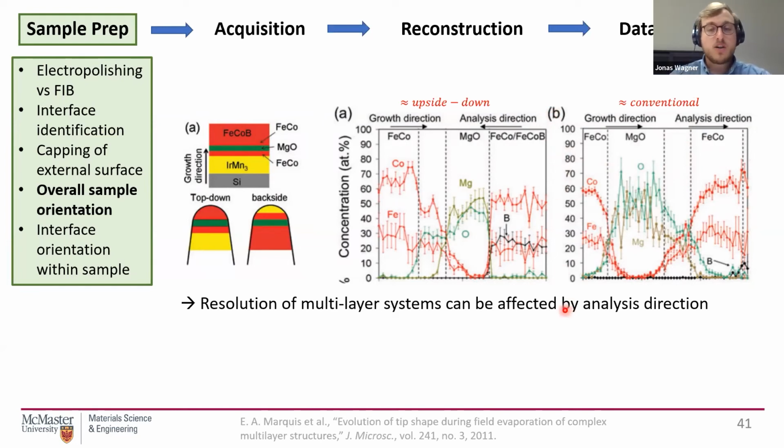Sometimes it doesn't work as well. For example, I also tried it with my sample, but because I had the oxygen contamination, having this oxygen contaminated layer between the post and the sample proved to be detrimental to heat transfer. And if I'm in laser pulse mode, it is the heat transfer characteristics that also influence my mass resolving power. So I, for example, continued to use the conventional way.